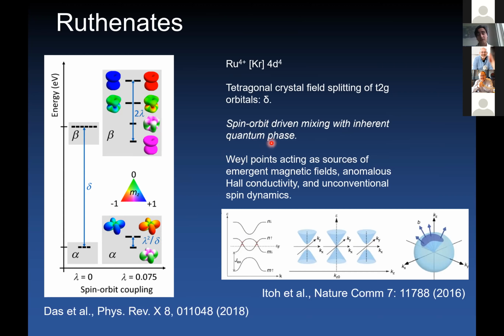So the consideration that I made above on the generation of Berry phases in the system through adiabatic transport is still relevant. So these ruthenates are systems in which Berry phases can be acquired. And this has been extensively discussed in the literature. So strontium ruthenate in the 3-dimensional limit is characterized by Weyl points. So these Weyl points occur when you have this crossing of spin split band structures that produce an avoided level crossing through spin-orbit coupling. So here you have a mixing as illustrated here, and these special points are sources of Berry curvature, of anomalous Hall conductivity, and interesting spin dynamics.